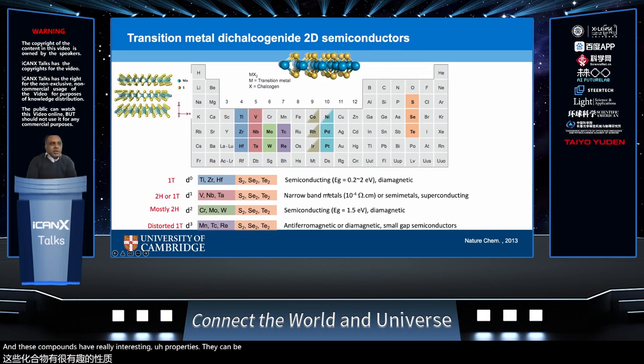They can be semiconducting, they can be narrow band metals. They possess interesting magnetic properties as well, and other condensed matter properties. The electronic structure of these transition metal dichalcogenides is primarily controlled by the transition metal. That is, the density of states from the transition metal lie closest to the Fermi level, so they dictate the optical and electronic properties. These chalcogens have energy levels that are deep within the gap and therefore do not contribute to the overall properties in a significant way.